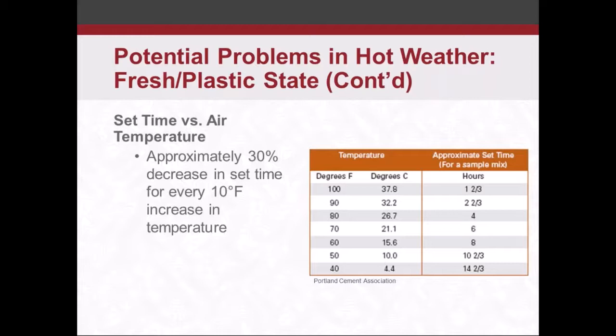So here's a chart that I copied from the Portland Cement Association. We can see it's about a 30% decrease in set time for every 10-degree increase in temperature. So that really goes both ways, in both cold weather and hot weather. So if we've got a project where we placed concrete last week and it was about 60 degrees, the approximate set time is about 8 hours. And maybe next week it's going to be 80 degrees on the same project, probably with the same crew of people working on the job. That set time is pretty much going to get cut in half.